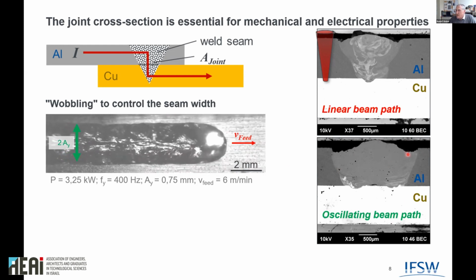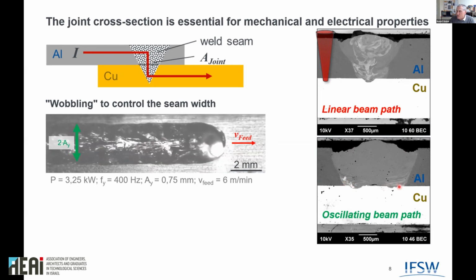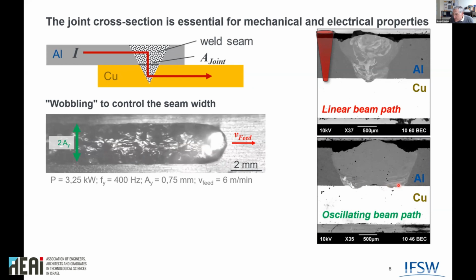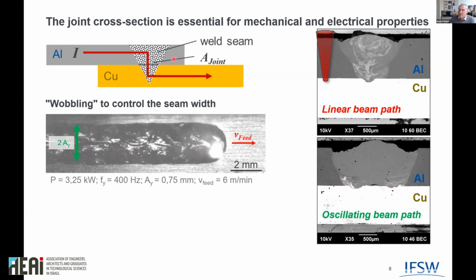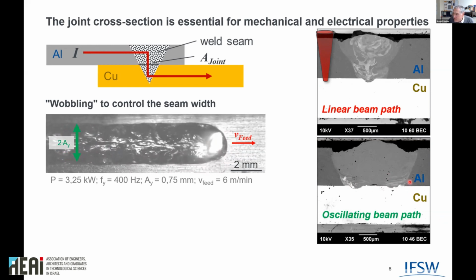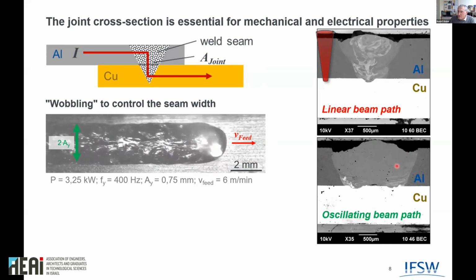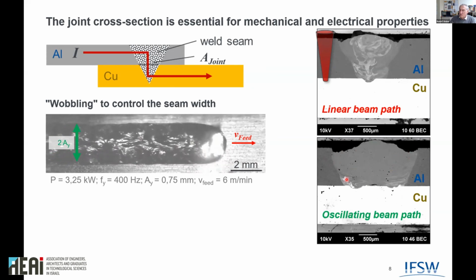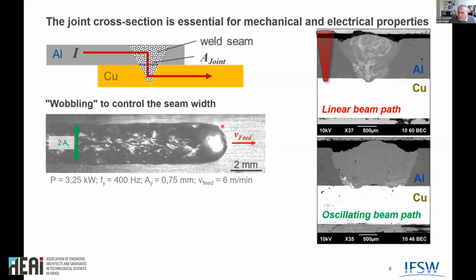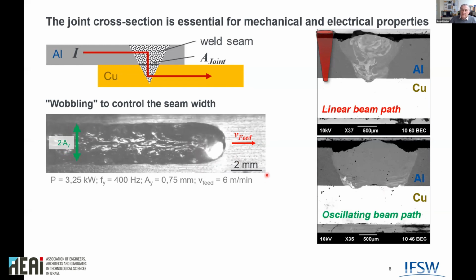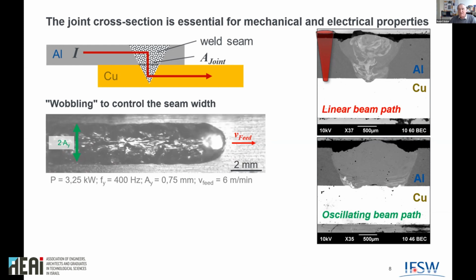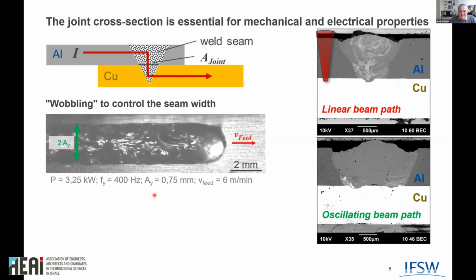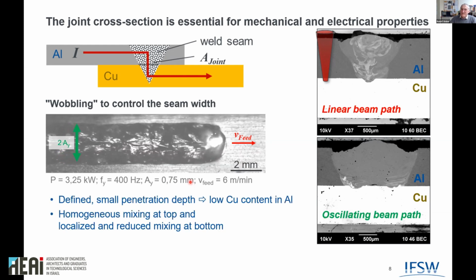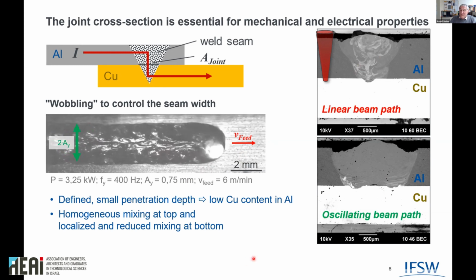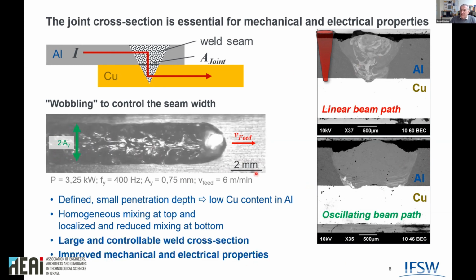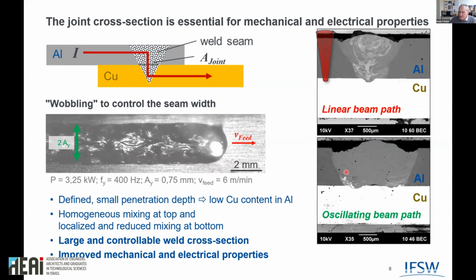If everything is adjusted well, you can see that the seam now is much wider, that we have, at most of the parts, a very nice cross section here where the current can flow through. And you can also see that the mixture of the material up here in the remainder of the weld seam is very low. So this is a very nice weld, which you can achieve by simply moving the beam over a surface, by having also, of course, the right power, the right frequency, and everything must be adjusted. If we just wobble, nothing happens. So it's really important to have the correct parameters. So we have a defined penetration depth, much more defined than here, and we have quite homogeneous mixing, which means we can really improve the mechanical and the electrical properties of such joints.